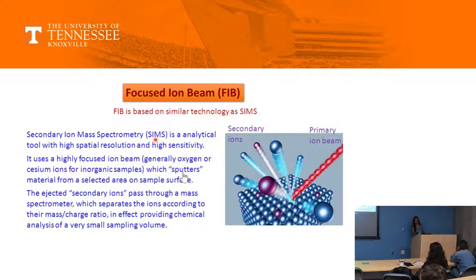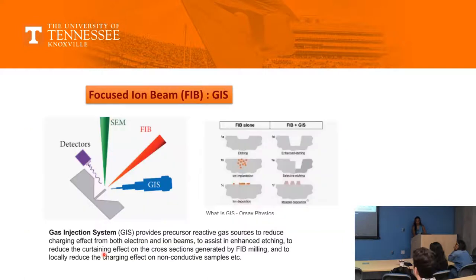The simple thing that we are doing is using a very highly focused ion beam to mill your sample. And this focused ion beam is attached to your SEM. Through SEM, you are looking at your sample, and through the focused ion beam, you are sputtering your material. So overall, we are just sputtering a material with a focused ion beam and looking through an electron gun. The schematic looks like that. I'll go a little bit faster through that because I covered it last time.